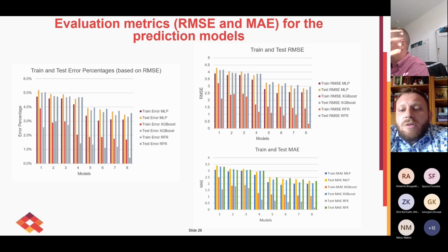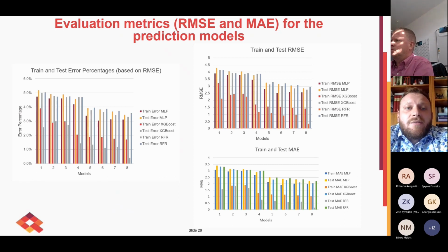You can see that as we go through models 1 to 8, these errors are decreasing steadily. And on the left, which is the most important, you can see the error percentages. The error percentages are calculated based on the root mean square error. So for example, when you make a prediction of, let's say, 75, you know that you will have plus minus from 5 to 3.5%. And this depends on which stage of the process you're in.